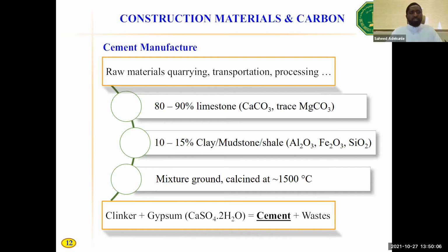And this is very important to examine what cement is all about. Cement is an industrial manufactured material which actually is very sensitive to carbon. Sensitive in the sense that the cement manufacture, as you can see, entails quarrying or collecting the raw materials, which are mainly materials from the earth. Okay, they are geologic materials, then transporting and processing this material into what we call cement. And as shown on the screen, about 80 to 90% of the raw material for cement manufacture is limestone, which is calcite or calcium carbonate, of course, with traces of magnesite.